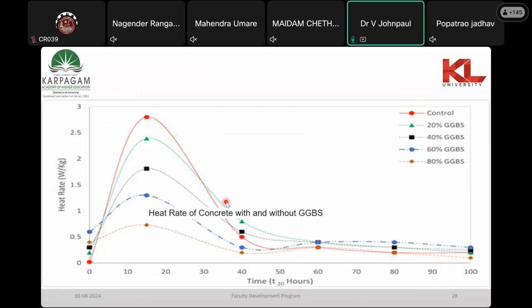These are the heat rate of concrete with and without GGBS. If you just look into this, this is controlled concrete. Peak hydration process. Then this is 20%, this is 40%, this is 60%, this is 80%. If you replace it to the maximum, there will be a huge reduction in the heat, this is around 0.5, this is around 2.5. So due to this, the pozzolanic reactions will be less, shrinkage cracks will be less. In the longer run, like what I said before, life cycle assessment, in the long run, better solutions compared to other things.